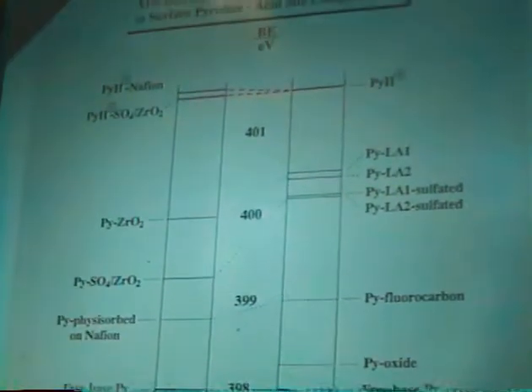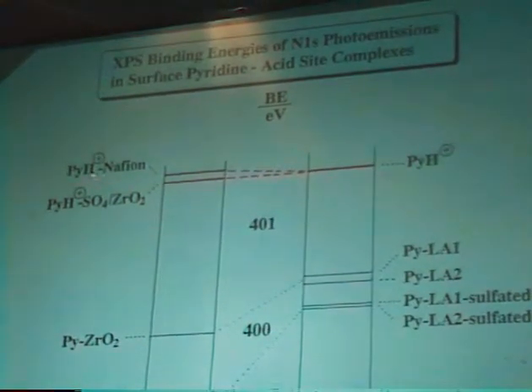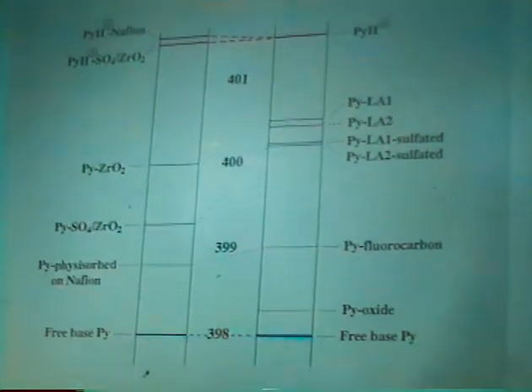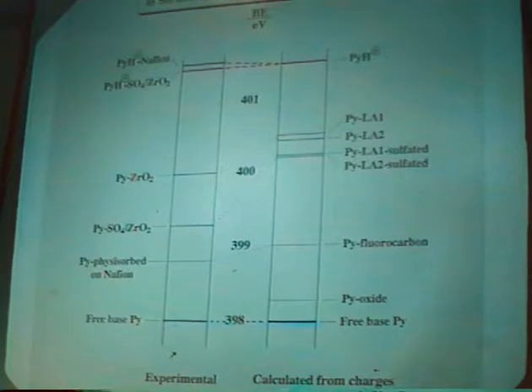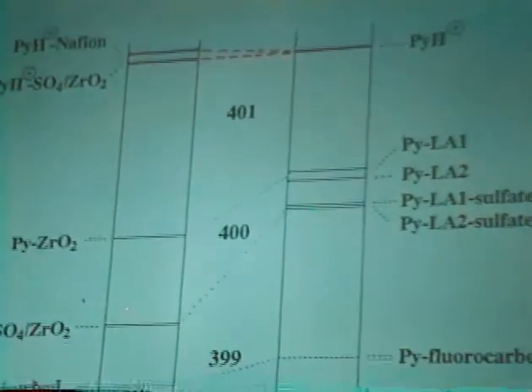When one looks and sees a catalyst with Lewis acid centers, one is then tempted to identify what these Lewis centers are. I have done similar calculations on the nitrogen shifts between model Lewis centers in which nitrogen is bonded directly to the zirconium that has the ionized sulfate groups on it and another time has an OH group. In each case there is a shift predicted of binding energy of the nitrogen down in the Lewis acidity. All of this put together creates a scale, an experimental scale and a calculated scale. The calculated scale is based on reference pyridine. The pyridinium calculated and the pyridinium on Nafion and pyridinium on sulfated zirconia are in nearly the same position. The Lewis acids, the calculations actually overpredict the binding energy and underpredict the shift that is due to sulfation.